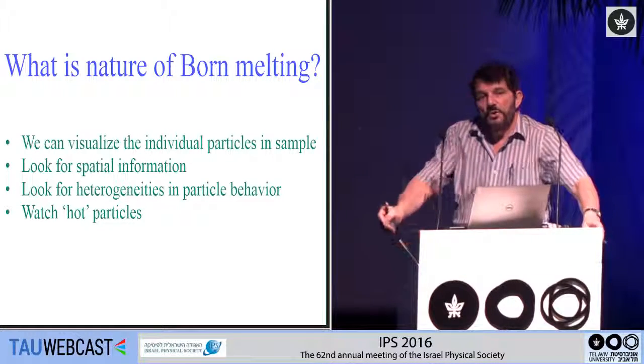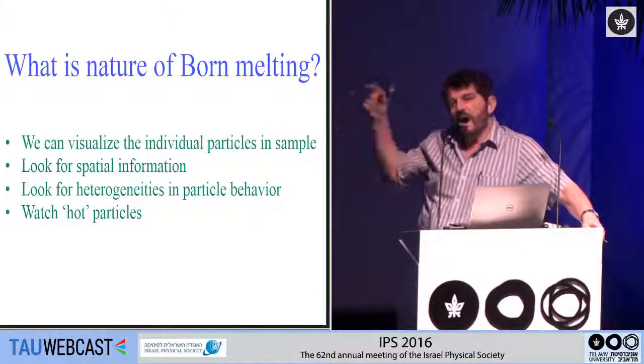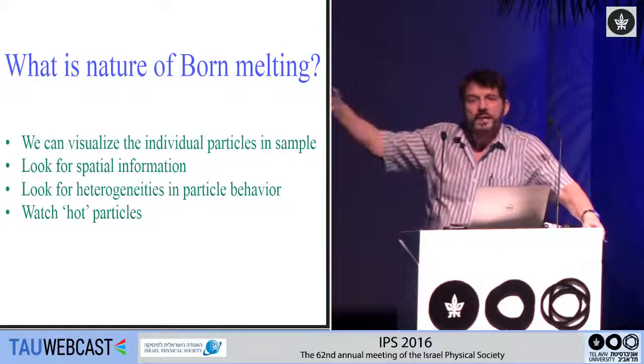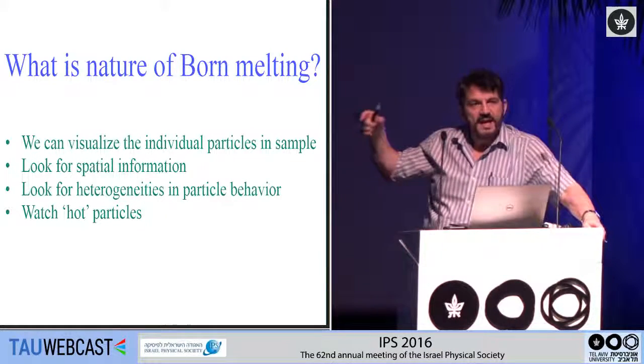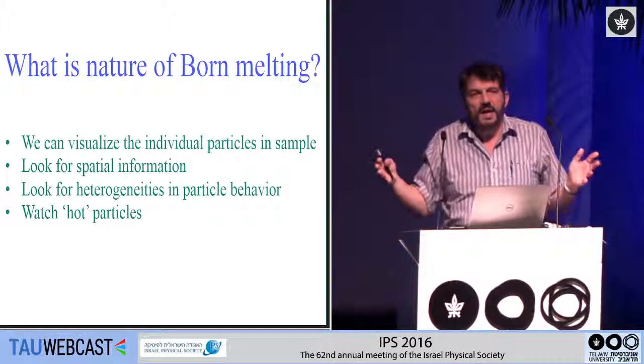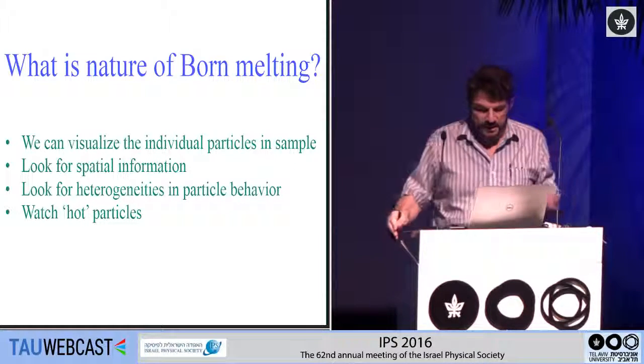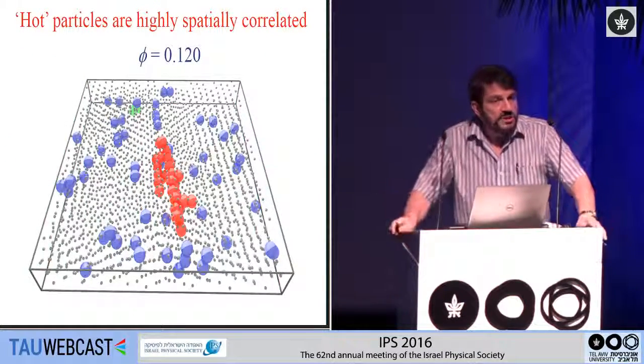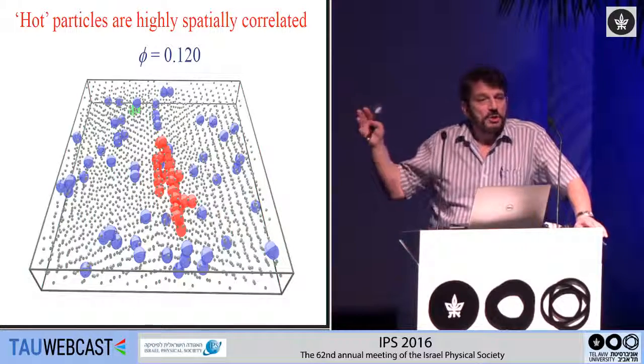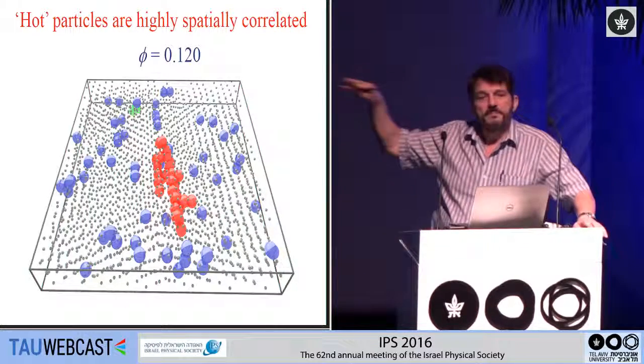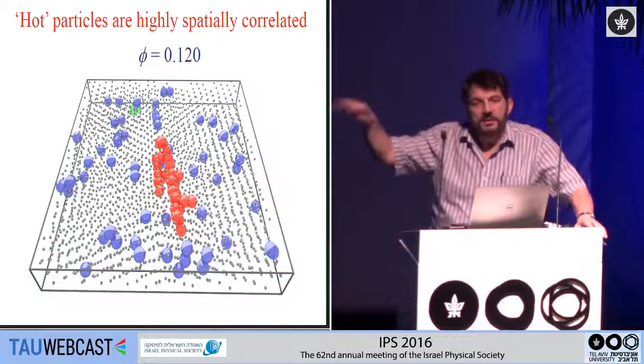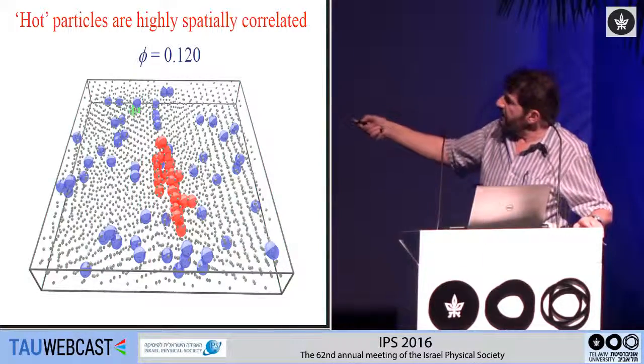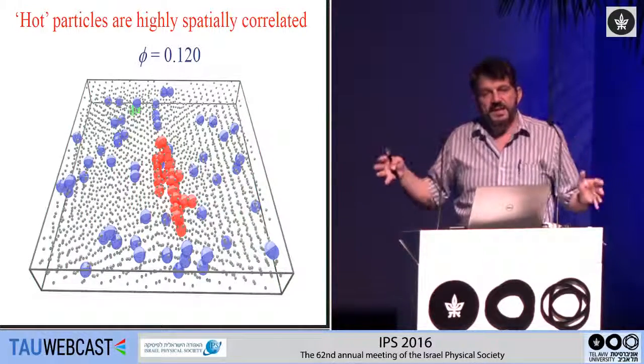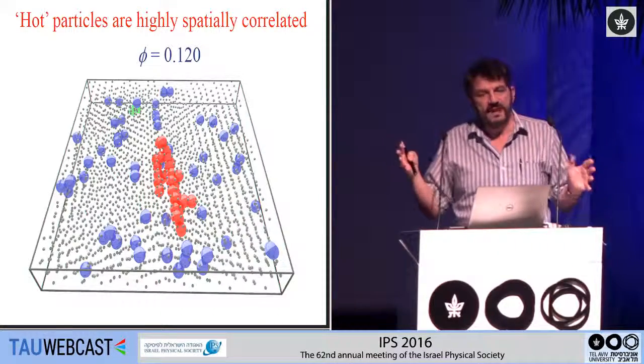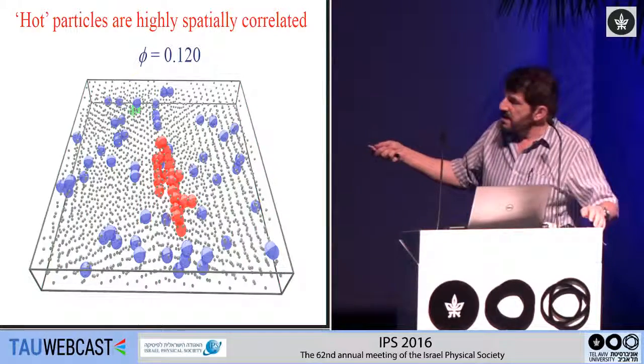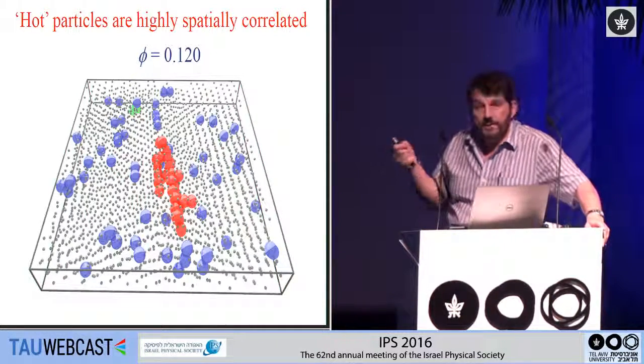particles. And in particular, we can ask, if we see these superheated particles, are there spatial correlations between the particles? Does one particle being superheated drive its neighbors? Is there some insight we can gain by looking at the spatial correlations between the hot particles? We can do this just looking spatially in the system. This is now just looking at a confocal three-dimensional image. We're imaging each and every particle. We're measuring the local fluctuations of the particles. And if their fluctuations are less than the melting value, so they're not superheated, we draw them as small spheres so you can look through them. The large spheres represent the superheated particles.